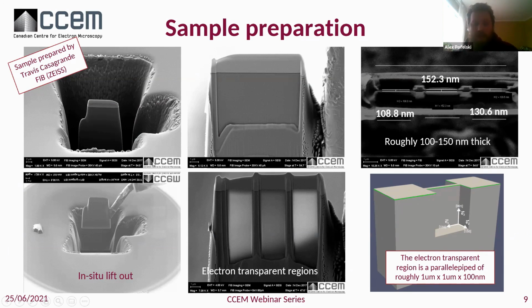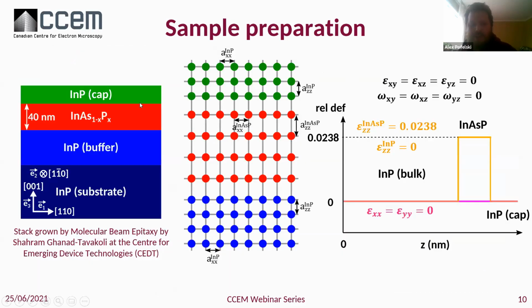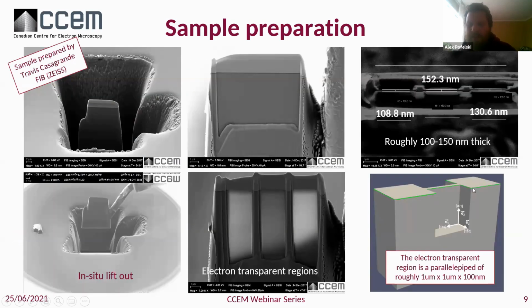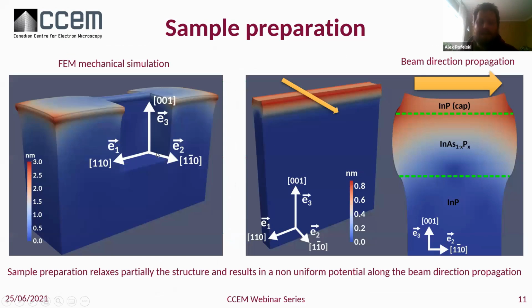And then we just put an initial stress into that little layer. What you have in green is the indium arsenide phosphide layer that has been given some initial strain. And then we let it relax to see how it goes. You have this bowing that is shown. Of course this is exaggerated, I think times 40. But this is the finite element method mechanical simulation of this strain relaxation on this 3D object.